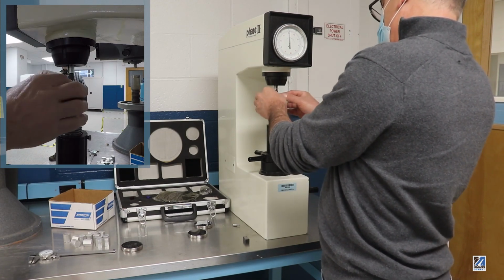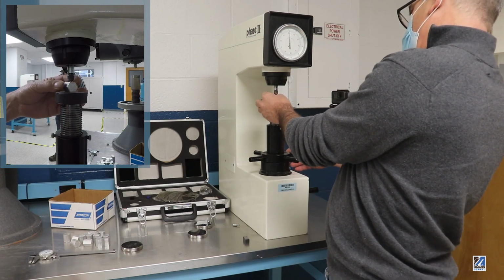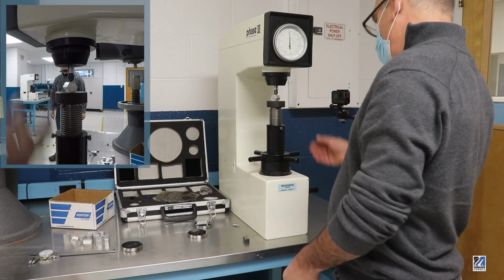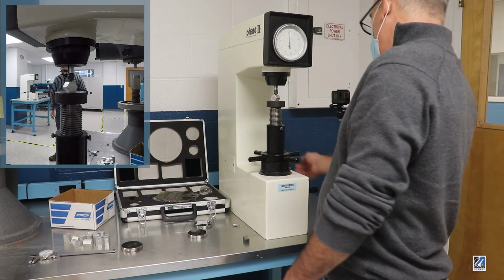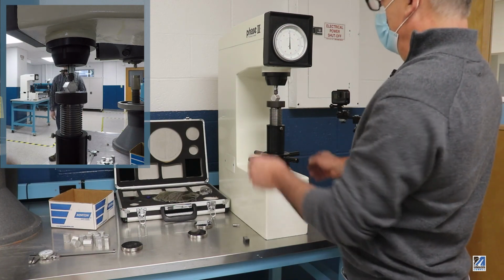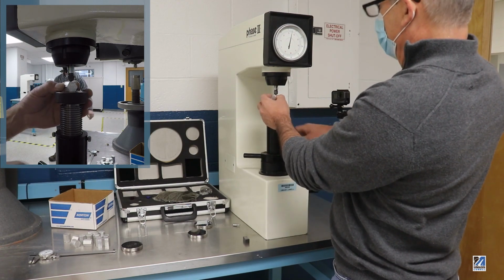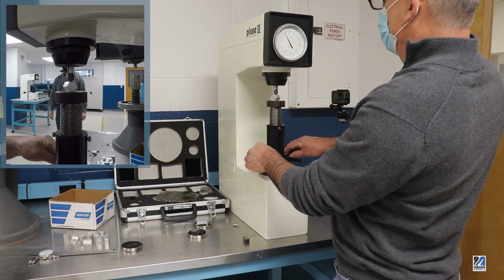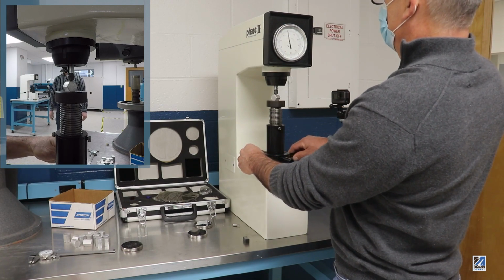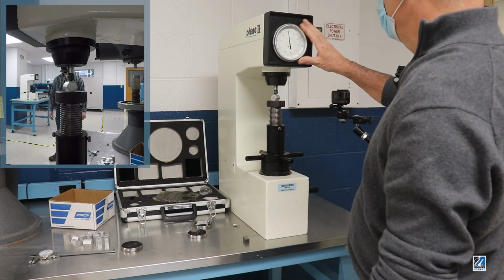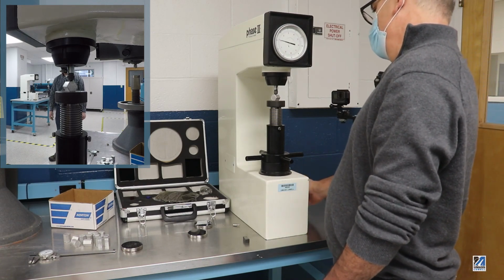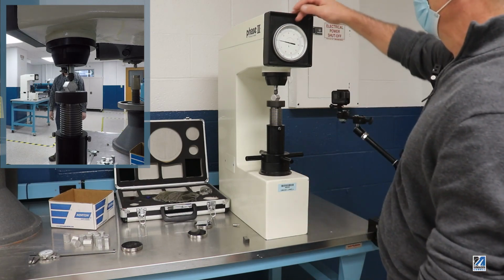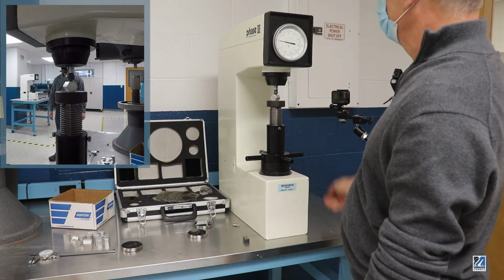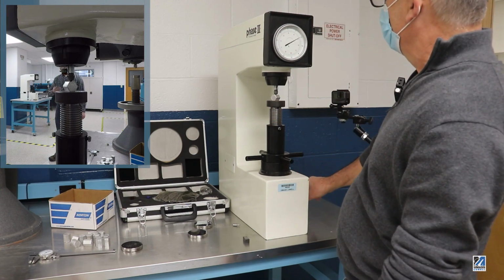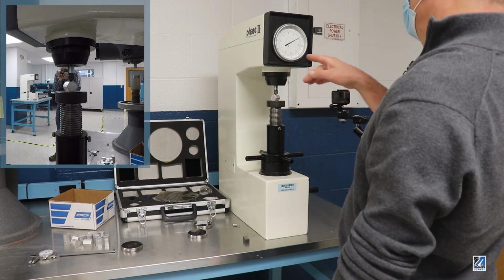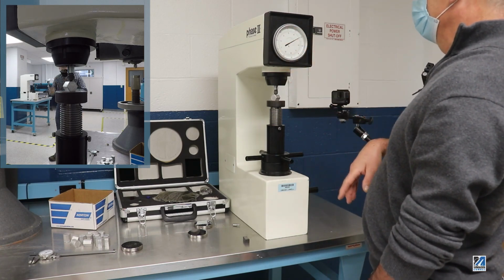So I'm going to go ahead and just do a quick test on that to see what I get for results on the Rockwell hardness tester. I'm all set up. I have my ball indenter, and I'm on a major load of 980. So what I'll do is I'll carefully preload with a minor load. Zero that out, apply the major load, wait for it to stabilize, if you will, and I'll pull that off, and if I read this correctly, I'm looking at a Rockwell B of approximately 51.